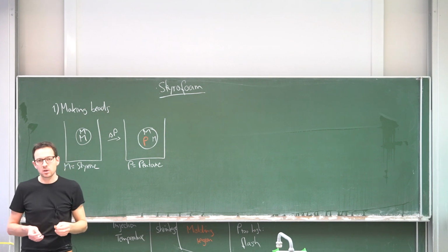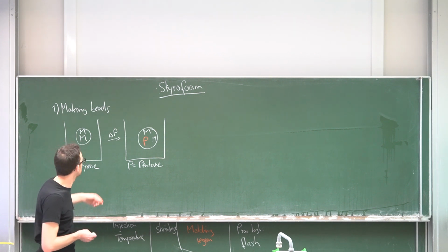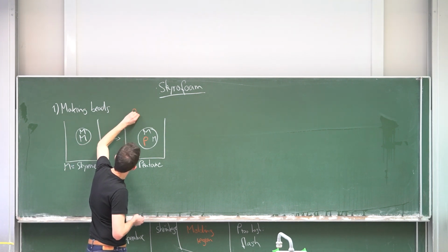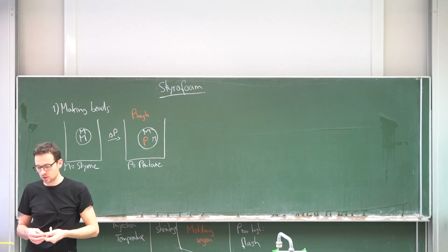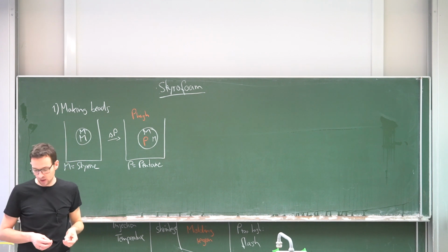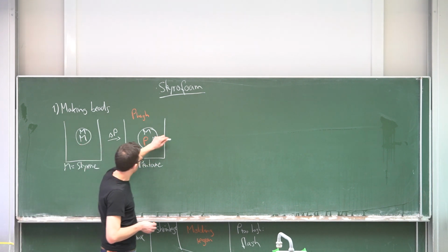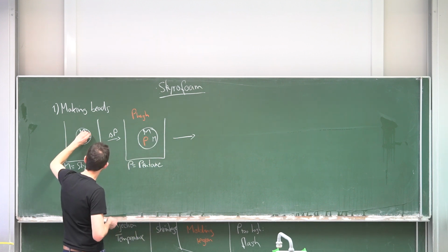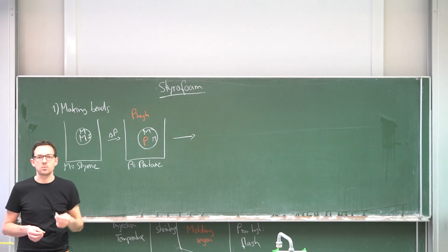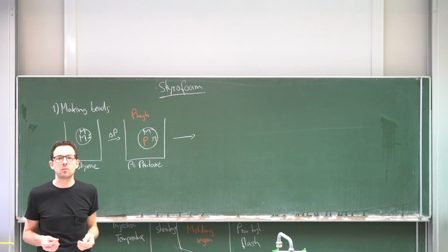So it mixes with the styrene monomer, but we want to ensure high pressure to make sure it stays in the beads, because it has a very high vapor pressure. So now we also, by the way, add an initiator. I just indicate this here, but I do not want to go into details about the chemistry. It's a simple radical polymerization.